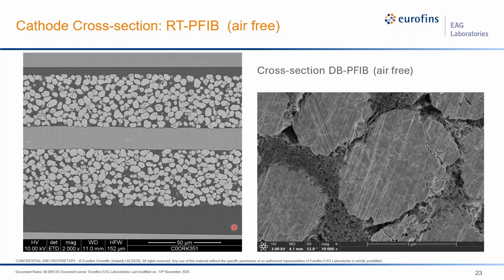And this is the example for the second one. As you can see, we got the cross-sectional image from the cathode sample with the use of plasma FIB. You can see the current collector in the middle, and the electrode on both sides. We can also see how the particles are positioned and what kind of size changes are happening for those particles. We can also compare before and after if the pristine sample is available. These are really helpful in some cases to understand what's really happening for the battery.